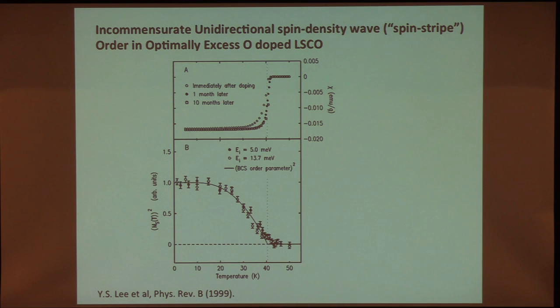There are lots of puzzling things about this. Magnetism in general in the cuprates has huge fluctuation effects. Why this transition looks so mean field-like is a little bit puzzling. The correlations involved are extremely two-dimensional, but the correlation length is 400 angstroms in plane. Why it doesn't lock into a three-dimensional order is a puzzle. But the puzzle I want to focus on right now is why is it that these two different broken symmetries that seem to have nothing to do with each other have exactly the same critical temperature? That's really weird.